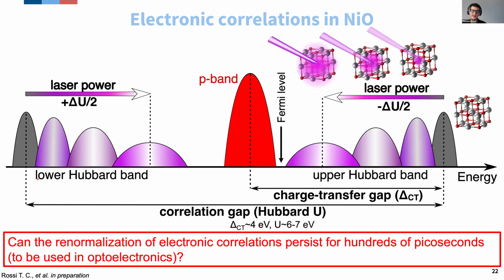One is called the lower Hubbard band, and the upper one is the upper Hubbard band. And the energy difference between these two is what we call the correlation gap. And the correlation gap is essentially the energy you have to pay to put 2 3D electrons in the same orbital with opposite spin. And in nickel oxide, this energy cost is of the order of 6 to 7 electron volts.